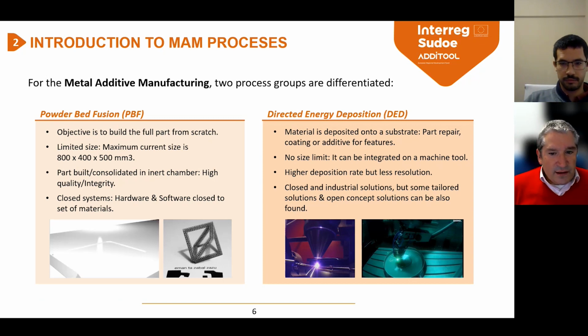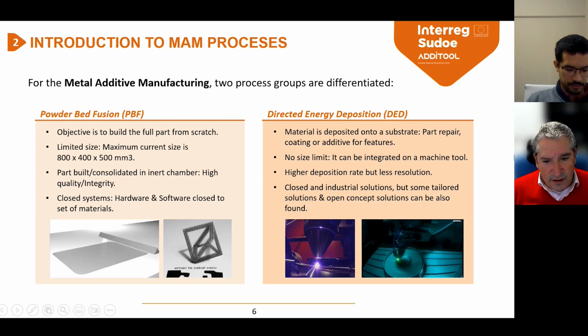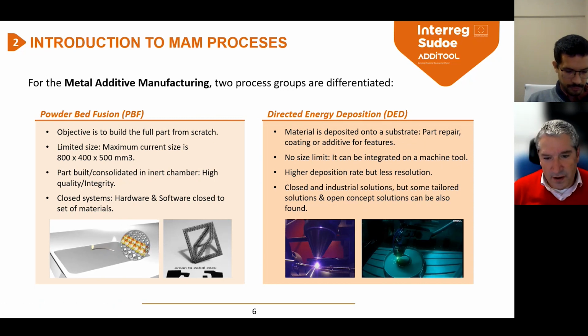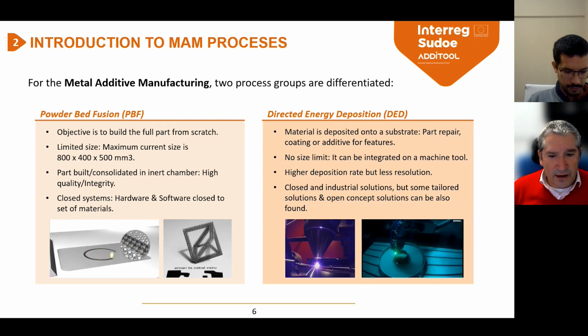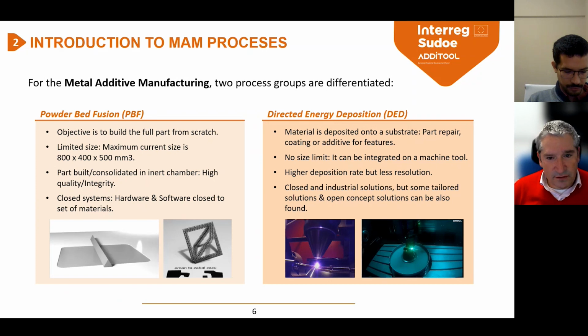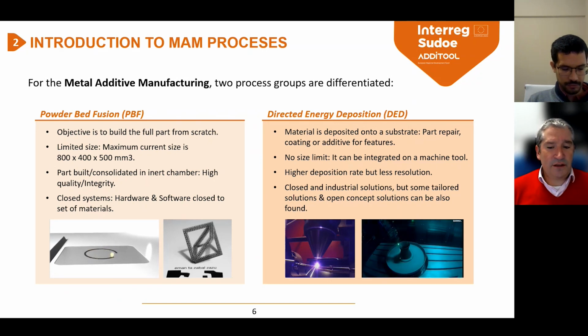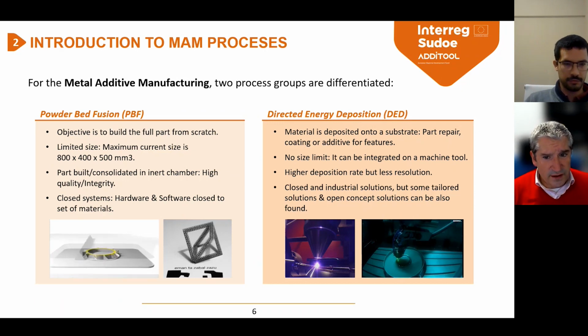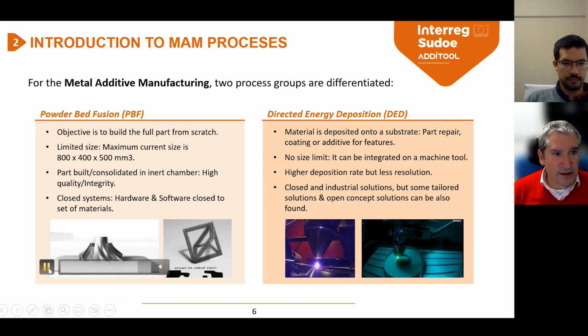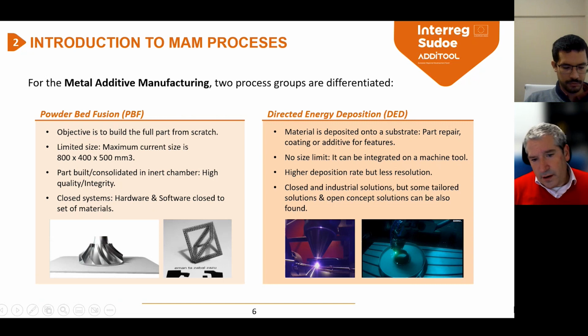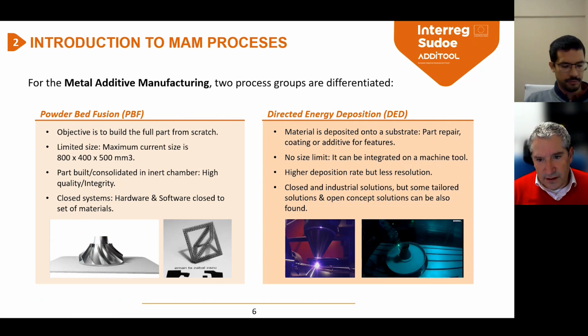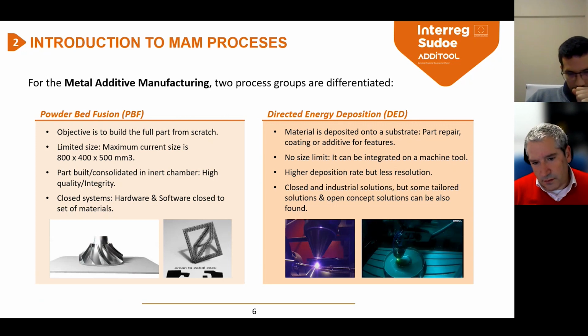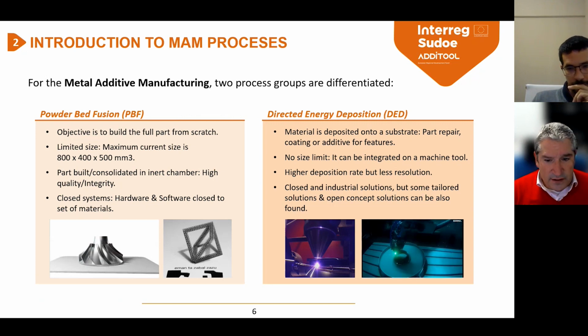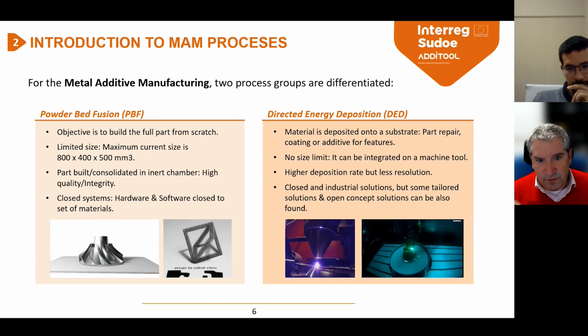On the other hand, we have the direct energy deposition processes. In that case, the idea is not to build the full part. We start from a previous part, from casting or forging, and we deposit material, injecting the material onto a substrate. This process is very useful for coating a surface, even part repair. If the part has been damaged or worn during service, we can inject material, add material in that area and repair it, put it in order again. And also we can build some features on a part, just going layer by layer for manufacturing a specific feature on a local area of a big part.